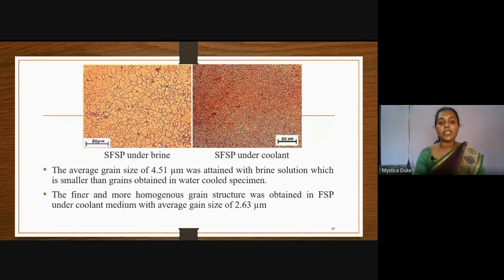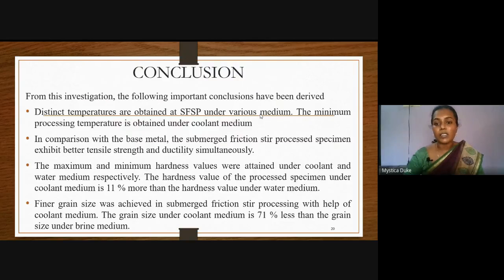And with brine, the grain size further decreased to 4.51 micrometer. And with cooling oil, we almost got an ultra-refined grain structure. Here you can see how refined the grain structure is, and the grain size reduced to almost 2.63 micrometer. So the conclusion from our study is that these three different mediums provided different peak temperatures. So depending upon the result you desire, you can use whichever medium you need.